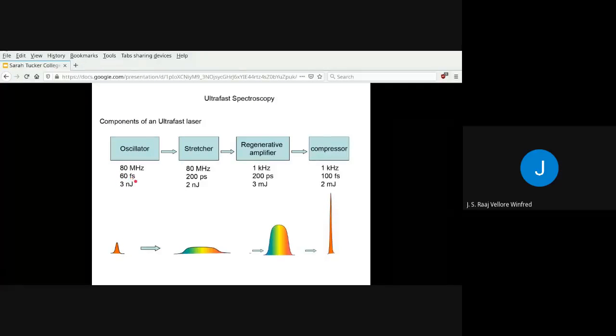Now, if you want to increase this energy, we need to stretch the pulse. By stretching the pulse, we are stretching it in time. We are taking a very narrow pulse and stretching it really broad. That's why it's called a stretcher. In the stretcher, the pulse width is stretched from 60 femtoseconds to 200 picoseconds. When you do that, the pulse energy also goes down because of the stretching.